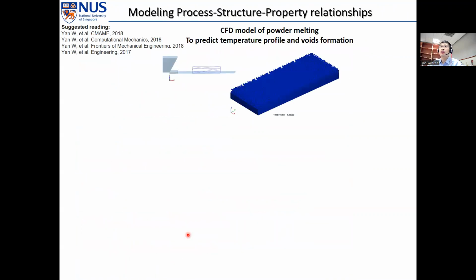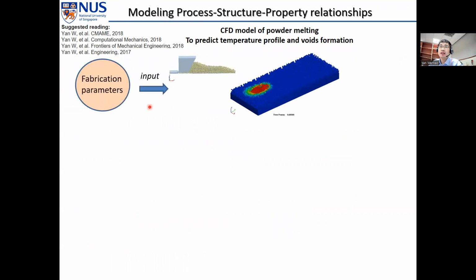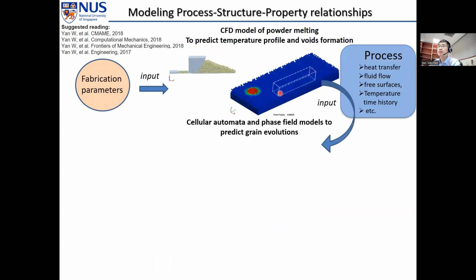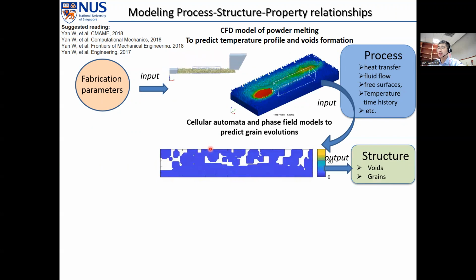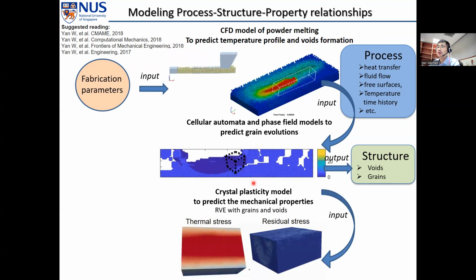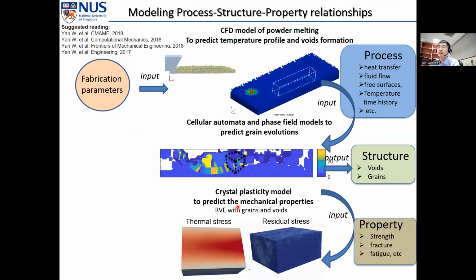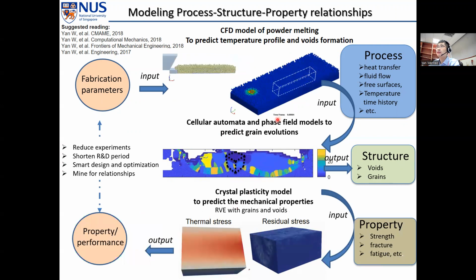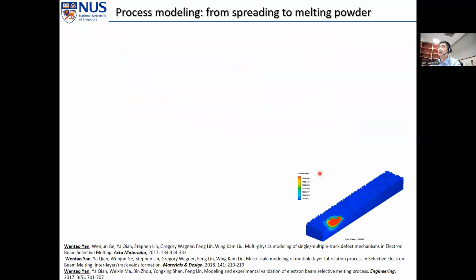So the overall framework is like this. When we get the fabrication parameters, we use the powder spreading model and powder melting model to simulate the manufacturing process so that we can predict the temperature profile and void formation. Then we input that into the cellular automaton and phase field models to predict microstructure evolutions. Further, we can use the crystal plasticity model to predict the mechanical properties and thermal stresses. With that, we can replace most of the trial and error experiments and accelerate the R&D process.